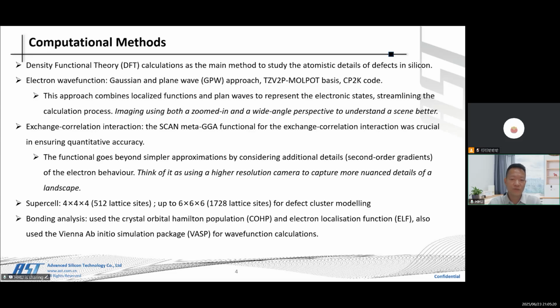Also, we use up to 1,728 atom lattice size supercells for defect cluster modeling. For bonding analysis, we use the crystal orbital Hamilton population, called COHP, and electron localization function, ELF. We also use the Vienna Ab initio Simulation Package, VASP, for wave function calculations.